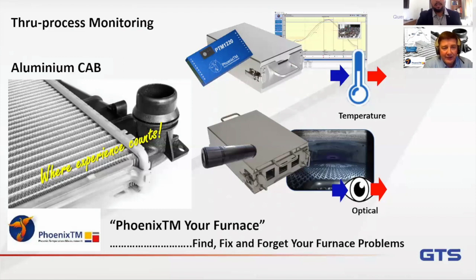As you quite rightly say, Victor, it will depend on the chemistry and the alloy you're using, and obviously the product itself. But what I would say is follow the recommendations of the alloy suppliers as to how long they suggest you keep it, the temperature at liquidus, how long you need to do that, and you can then use the profile trace to actually control or govern whether or not you're within that time window that they're recommending for that material.